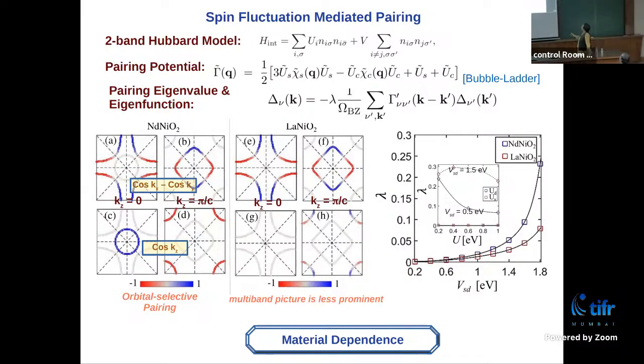So this is the superconducting coupling strength plotted as a function of the interorbital interaction V, and that has a very strong effect. By making it a little larger, you actually have the lambda shooting up.